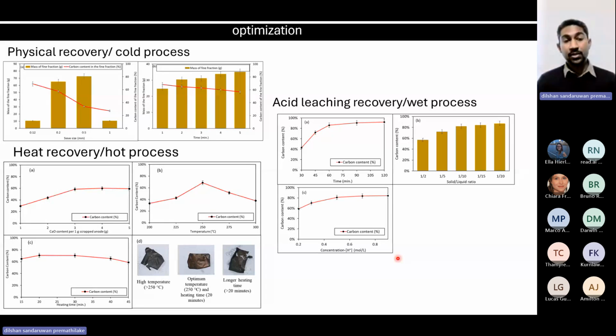In the heat recovery or the hot process that I used, I tried to use elevated temperatures without using any other chemicals. But the problem with the elevated temperatures was that to decompose these PVDF binders, I have to elevate my temperature up to 500 to 600 Celsius degrees, which is not a good thing, because it's going to elevate my environmental footprint again.